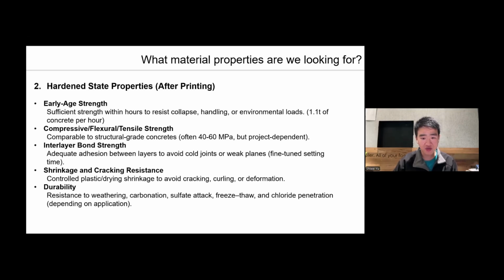The next one is the mechanical strength, just like the conventional concrete: the compressive, flexural, and tensile. Our current material typically reaches 40 to 60 megapascal at 28 days, which is comparable to the structural grade concrete. And we also need strong interlayer bond strength, which I mentioned before. Each layer has to adhere well to the one below to avoid a cold joint. This is managed by carefully balancing the setting time and mix design.